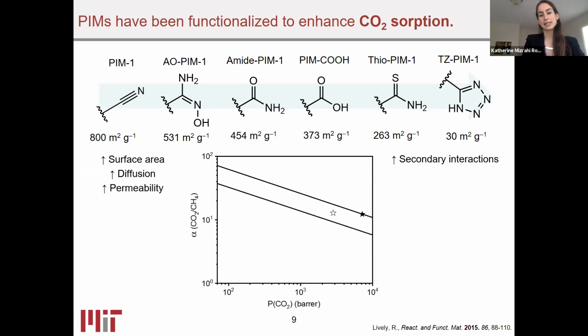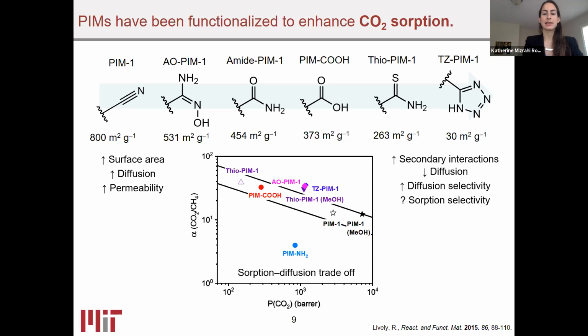And when this is tuned or changed to various different functionalities, you can see that the permeability decreases for essentially every single sample, whereas selectivity sometimes increases. But in certain cases, such as that of amine PIM1, the performance is completely destroyed after functionalization. And this is because of the reduced diffusion that occurs after increased secondary interactions, as well as the reduced BET surface areas.